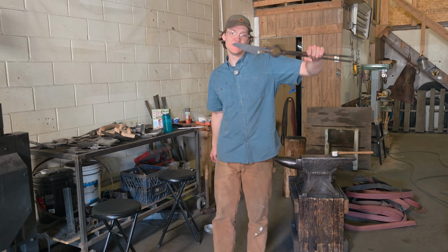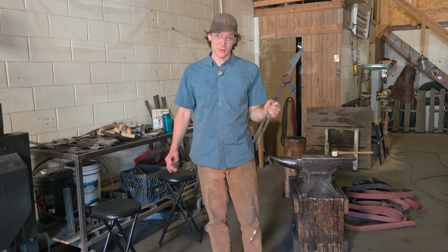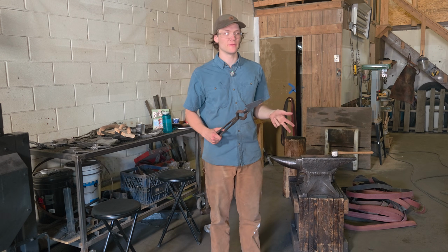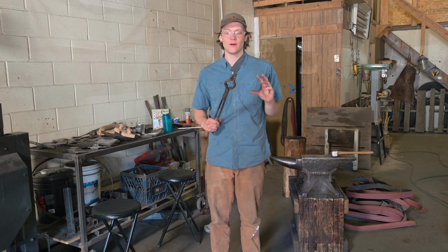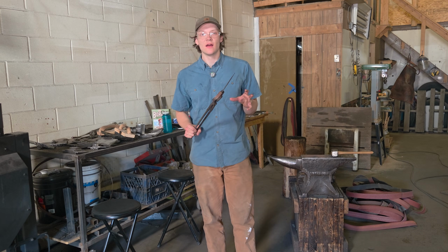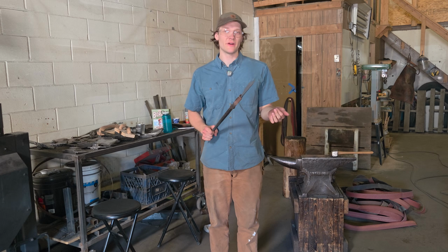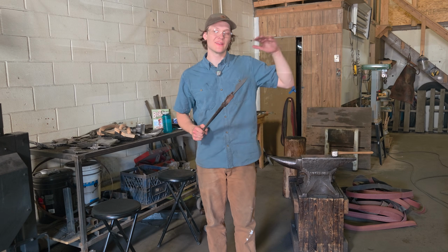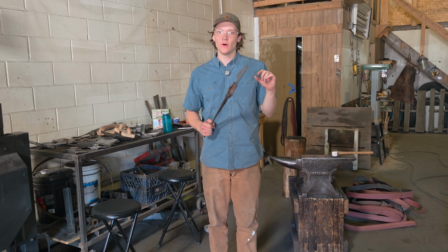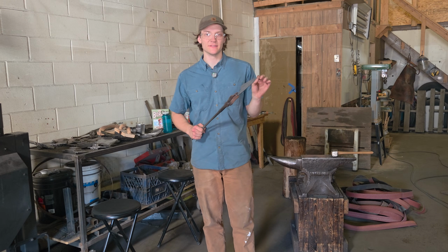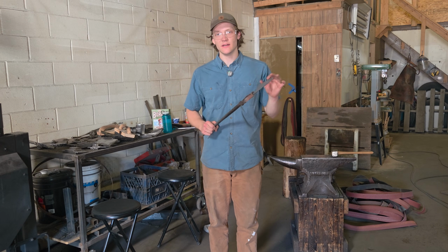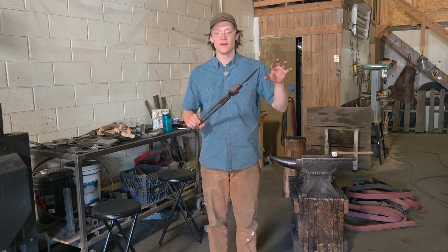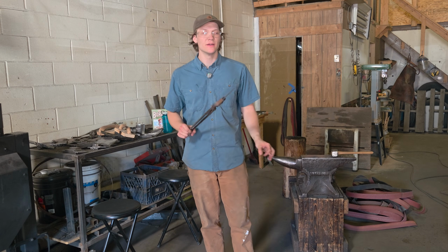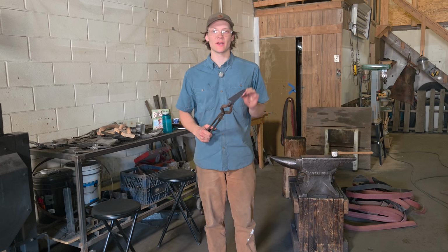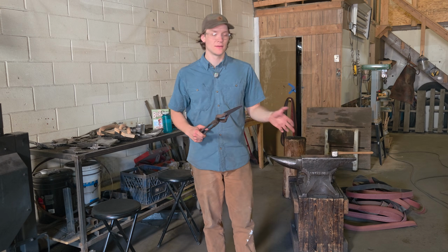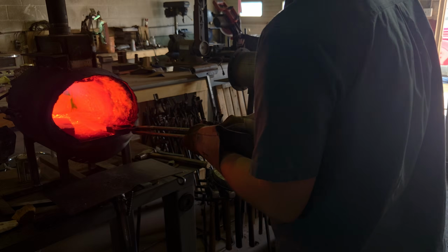Now that all the forging is done on this Honesuki, I'm going to take it through my normalizing and grain refinement cycles. Now, I'm going to do something special for this steel. I'm going to do a lot of extra grain refinement cycles at low temperatures, keep getting lower and lower, because I want to bring out the carbide banding in the steel so you can see a little bit of a watery pattern on the finished blade. It probably won't be super noticeable, but I want to see how much I can bring it out. So we'll see.